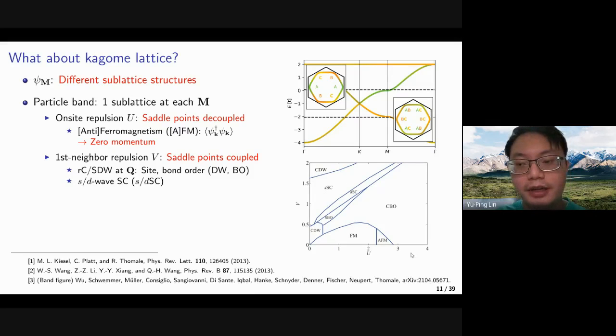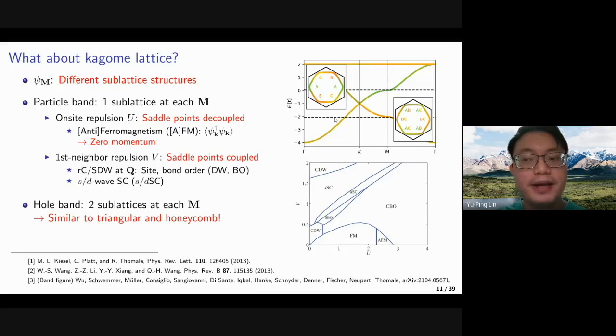So here, some people have done the functional renormalization group. You can see that if we introduce U, there will be zero momentum instabilities. And if we introduce V, there will be finite momentum instabilities, which could be either charge or spin density waves. And it could be either site or bond order. Meanwhile, similar to graphene and triangular lattice, there could be superconductivity. And for the lower band, the saddle points could be coupled already with on-site repulsion. So the phase diagram will be similar to the triangular and honeycomb lattices.